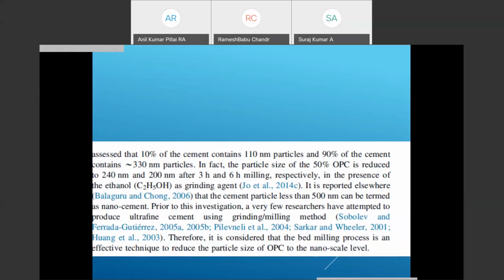So after grinding in bead milling, it has been observed that 10% of the cement contains 110 nanometer particles, and 90% of the cement contains 330 nanometer particles. In fact, the particle size of 50% OPC is reduced to 240 nanometers and 200 nanometers after 3 hour and 6 hour milling respectively in the presence of ethanol as grinding agent. It is also reported that cement particles less than 500 nanometers can be termed as nano cement.